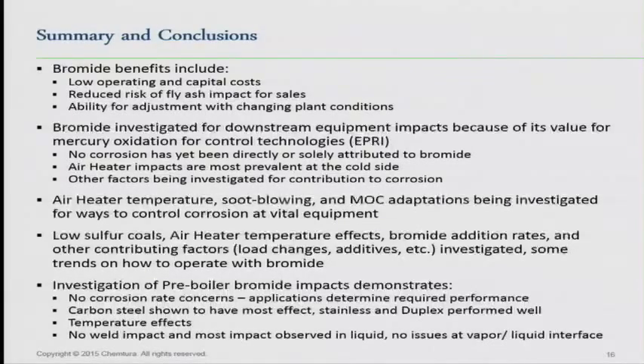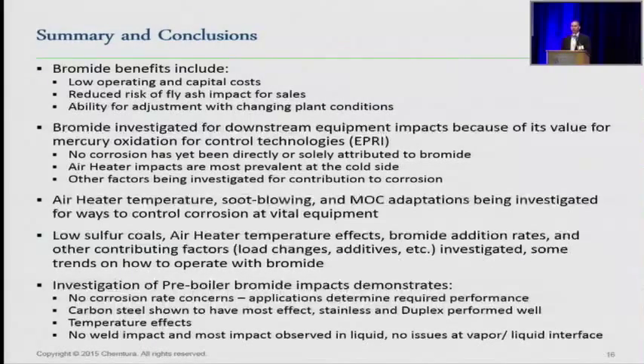And I think that's probably one thing that necessarily wasn't as big of an issue when you had plants running full out on a more consistent basis, but as we've seen over the last few years, is a bigger issue. Looking downstream with the EPRI study, and again, I give them a lot of credit there, Katie and Nanda, they're doing a good job with that, looking at the balance of plant issues. For the most part, they really haven't attributed anything to bromide, but again, I think the more that they see over time and they see the data, it's very interesting to see the trends that are popping up, especially with the kind of coal you're using and how you're operating that plant. So if you're using a PRB and you're adding bromide and you're starting to see corrosion and you want to start blaming it on something, bromide is probably your cause, but you probably have some abilities there to tweak how you're running as well to still be able to get by using it and not have the issues.